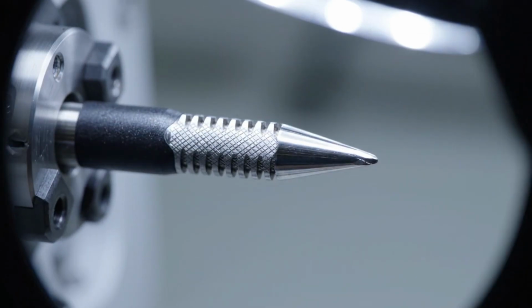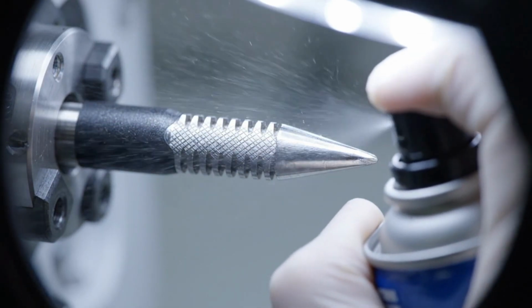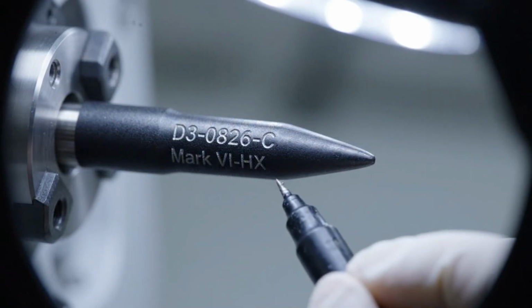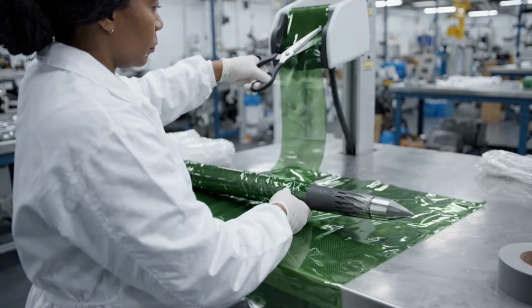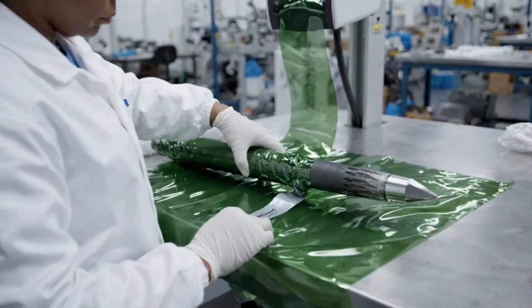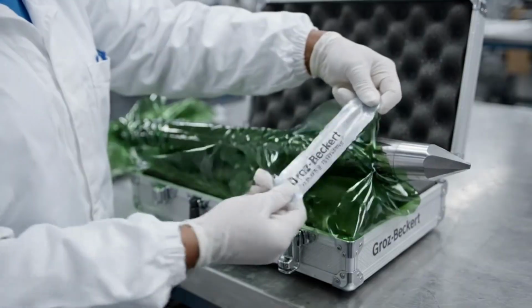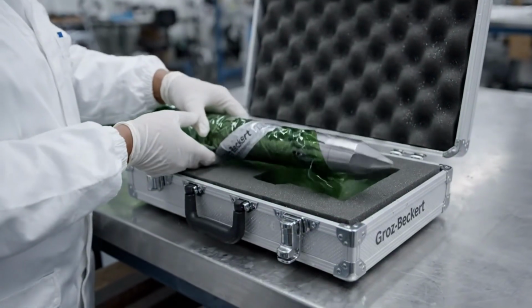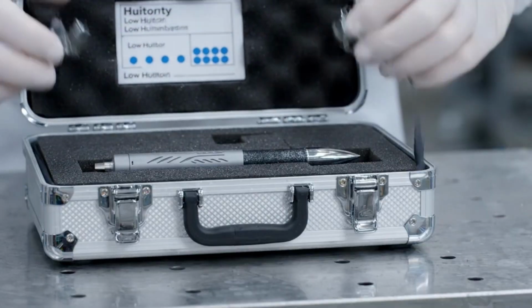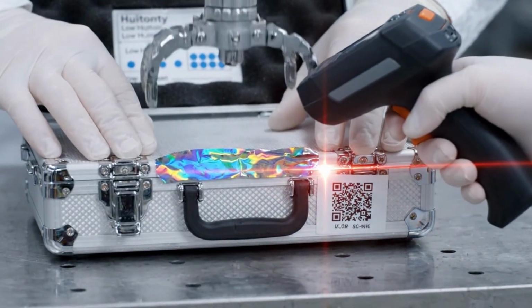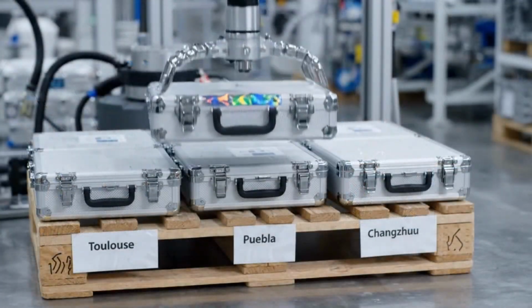The 40x visual inspection is the final human interaction with the needle. After this, it will be sealed in its case. The VCI film releases molecules that form a 1-molecule thick protective layer on the steel surface. The case is sealed at less than 30% relative humidity, an environment in which the needle could rest for a decade and emerge as perfect as the day it was packed.